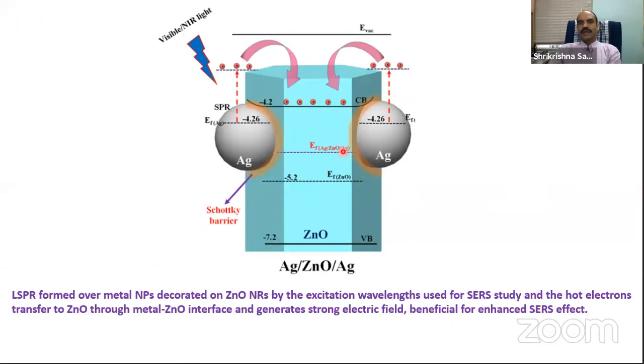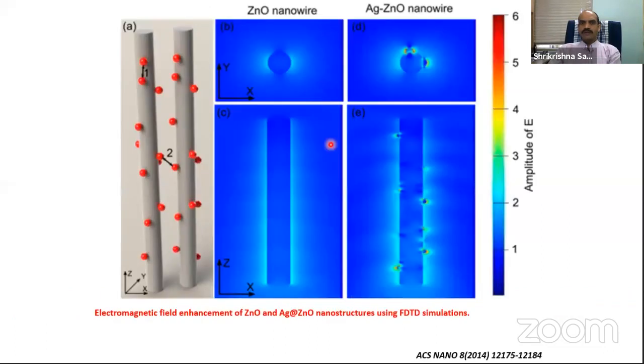What I can do is grow these silver nanoparticles on this zinc oxide. And what will happen? Of course, these silver nanoparticles will have the hotspots, basically the electric field will be more. However, zinc oxide alone will not have any electric field enhancement, because it is not a plasmonic material.